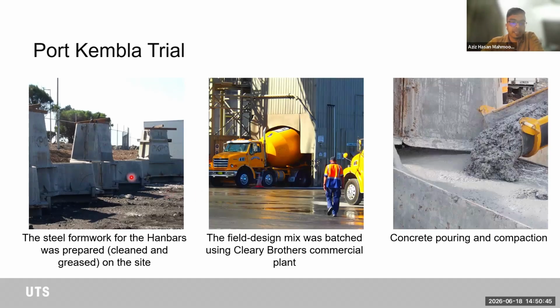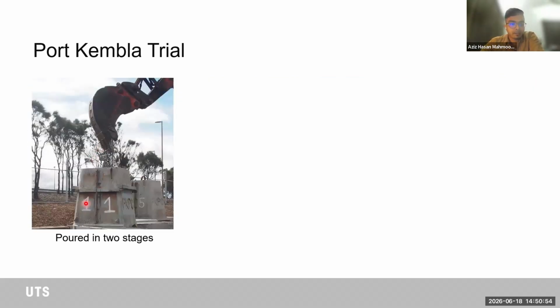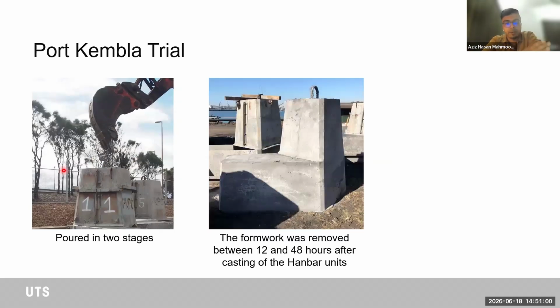So we filled out the legs first and waited for the legs to sort of stiffen up before we poured the rest of the concrete on the top leg there. So here's a picture of concrete pouring on the top of the formwork. And they were left within the formwork for 12 to 48 hours.